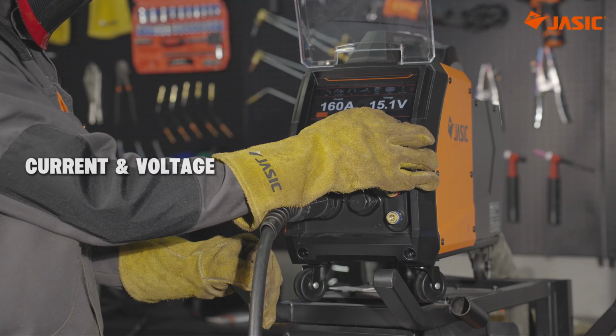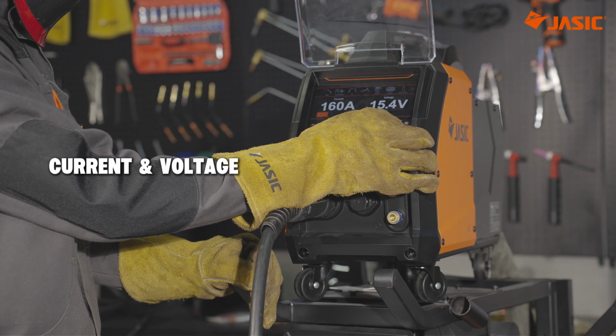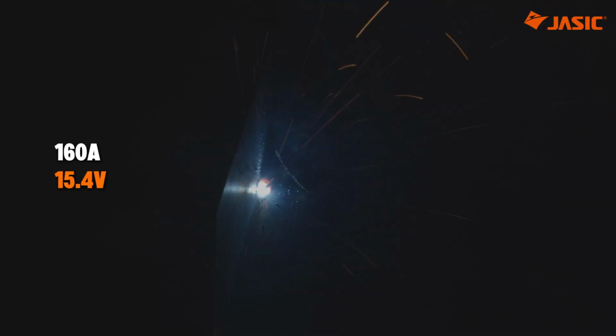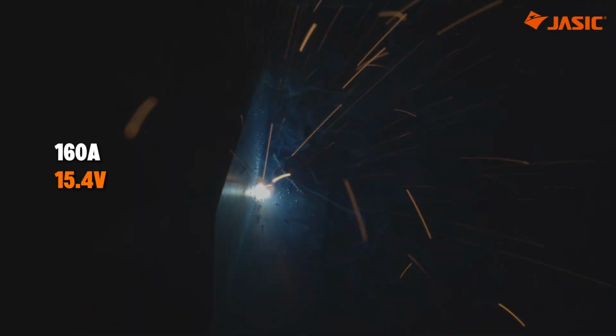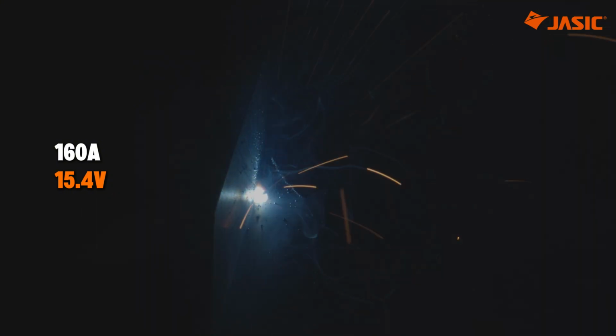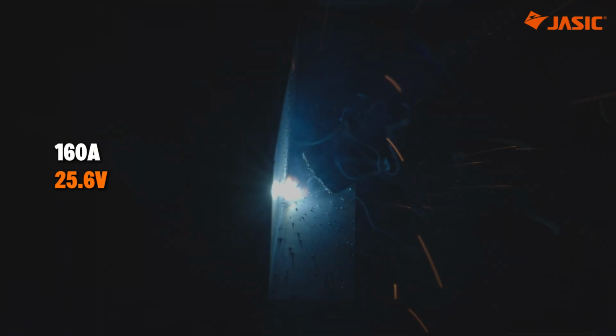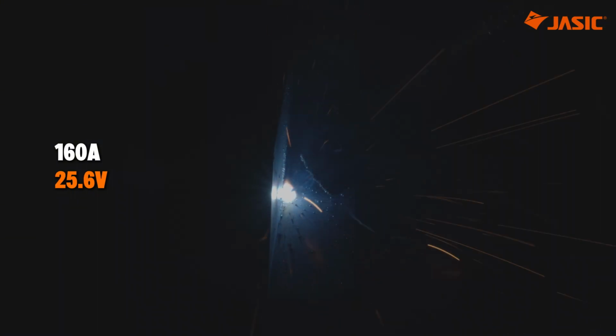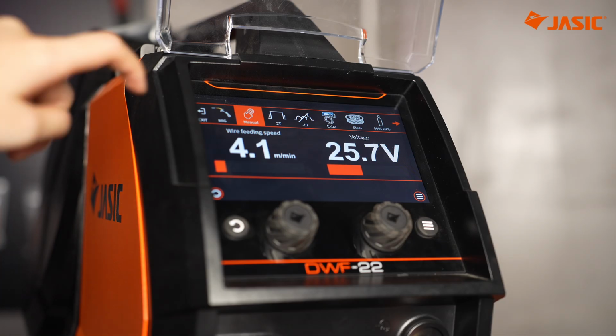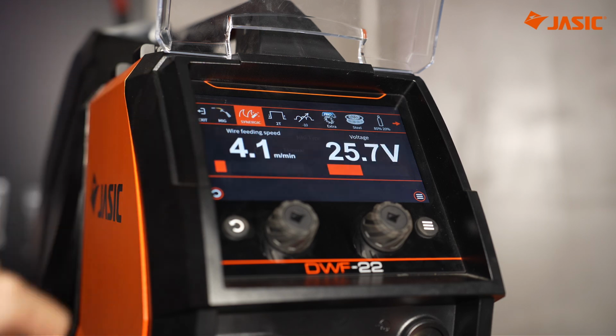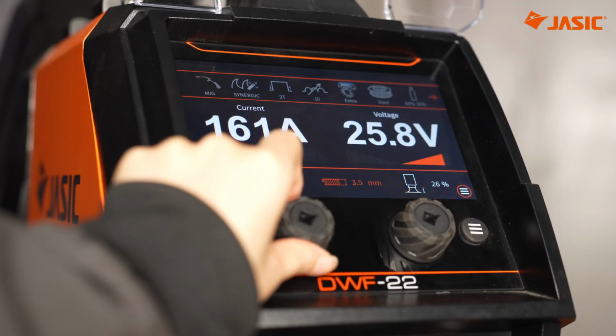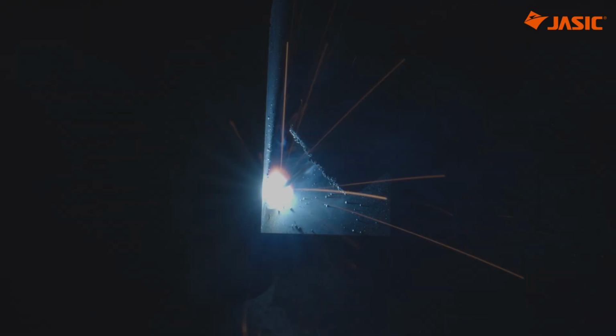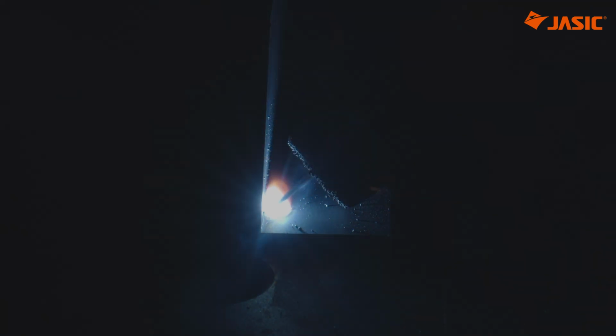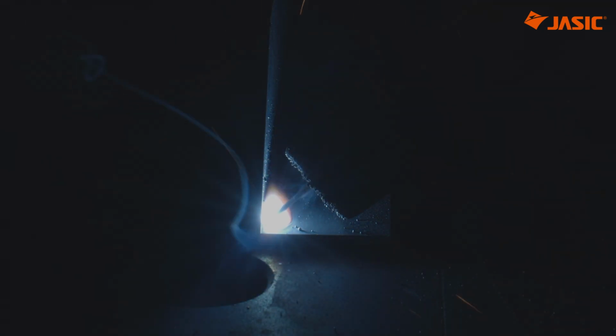Current and voltage also need to match. If the voltage is too low, the arc becomes too short and the wire keeps short circuiting into the weld pool, creating excessive spatter. If the voltage is too high, the arc becomes too long, increasing arc pressure on the droplet and making metal transfer unstable. The best approach is to fine-tune the voltage after setting the current, or simply use a synergic mode if your machine has one. A smooth, consistent, sizzling arc with no loud popping usually means the settings are well matched.